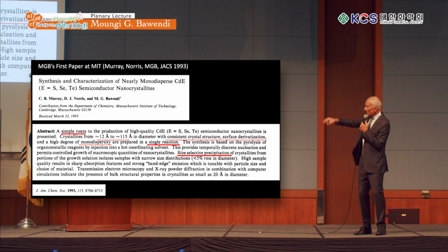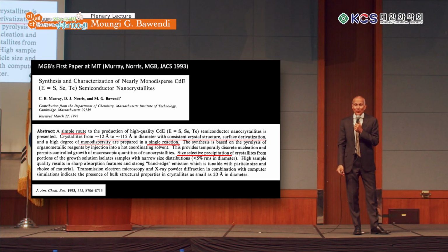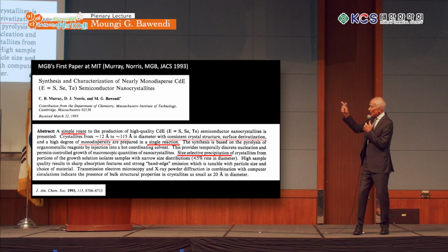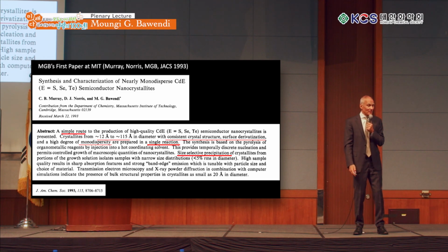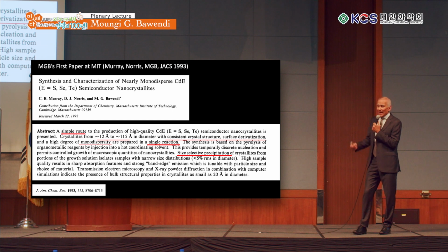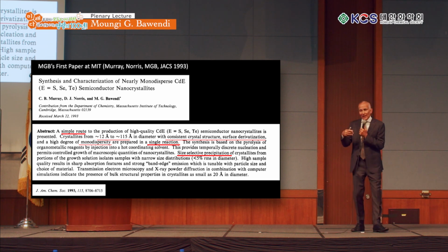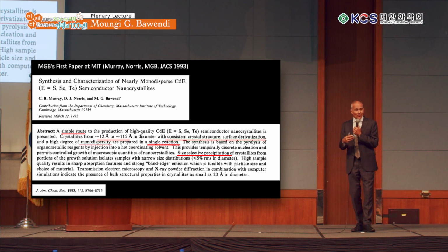And the size-selective precipitation was a way to purify this nanomaterial. You know, if you're a chemist, you run your sample through a column, you crystallize it, you find ways to purify your new product so you can characterize it. And so we also needed to do that. So that's the selective precipitation part. And after doing that, we were able to get samples that we were able then to do physics with and really begin to understand this process of evolution from atom to bulk.